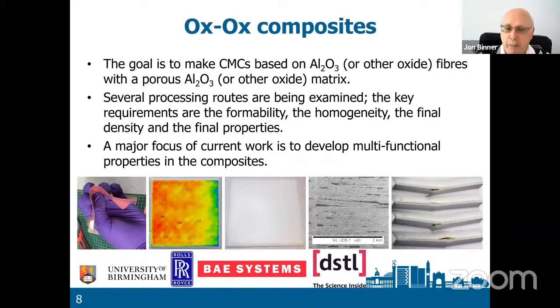There, in the middle picture, you have a photograph of the sort of composites that we are making. You've got a microstructure showing you the microstructure of the materials, and then on the right-hand side, these are test bars that we have broken. And the crucial thing here is they have not snapped in half. They have bent. The fibers are still connected in many ways, and so failure is not catastrophic. Failure is gradual, and that's exactly what you want in these ceramic matrix composites.